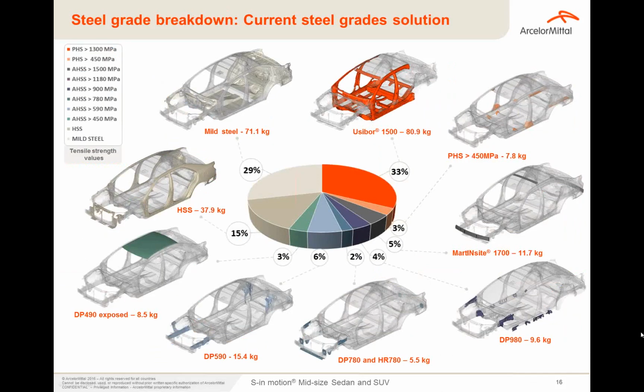So here I will go more into detail now to highlight the solutions leading to these very light body-in-white structures. The S-in motion mid-size sedan pie chart here shows the applications of ArcelorMittal steel grades. So you see that we applied on the sedan version more than 33% Usibor 1500 to build a very strong safety cage, as shown on the picture. And MartINsite and dual phase steel grades also account for 20% of very important, or I would say key, parts of the body-in-white to also optimize the weight saving. We also applied our new DP490 grade for exposed panels, and I will come back to that later on.